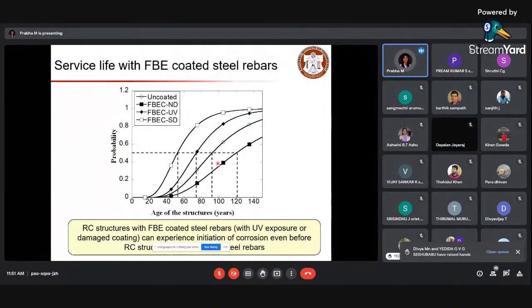So here you can see the service life predictions with respect to FBE bars. When you use the FBE bars properly, it will help you. You can see this one is the conventional rebar without any coating, and another point to notice is that these epoxy bars tend to degrade when exposed to direct sunlight for a longer duration.